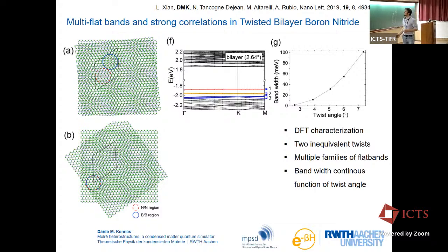All right. The next difference, and I hinted at that before: boron nitride is a very good insulator, it has a huge band gap. That's why we're using it all the time. So when you look at the behavior of the bandwidth of this red band here, for example, then you will see that at small twist angle, this does get flatter and flatter, but there are no magic angles. Even if I would continue this, there's no magic angle dip structure that we have seen. All right, so that's, again, good for experiments, maybe bad for intellectual richness.